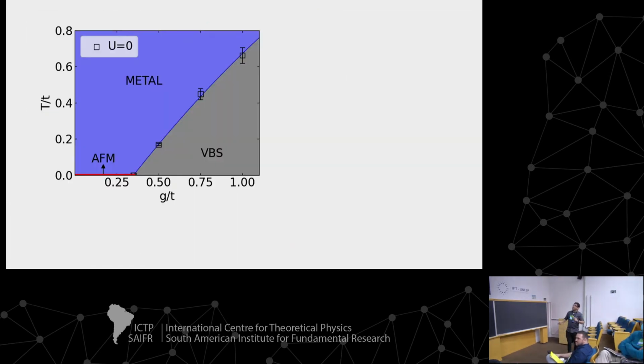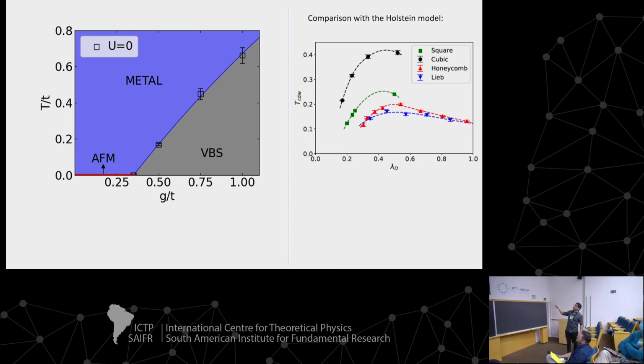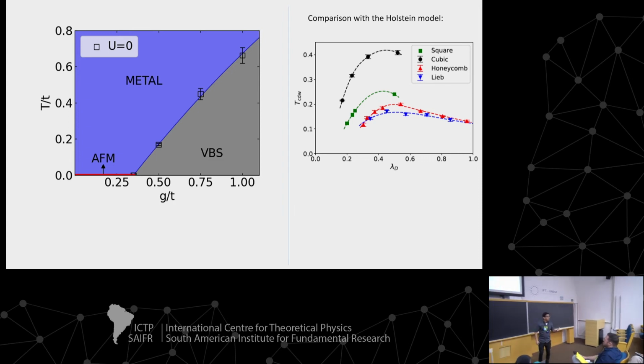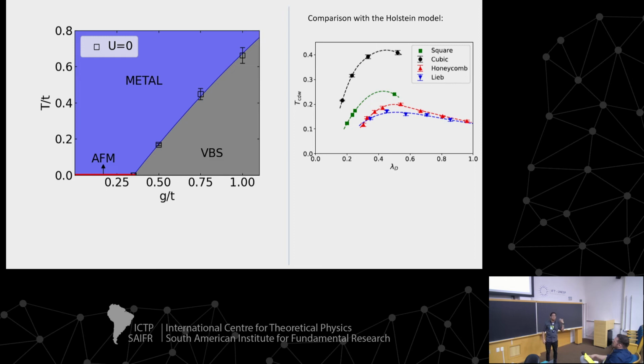And the main result that Sebastião has shown is basically we have this phase diagram, finite temperature phase diagram, in which the temperature increases a lot. And this is a lot indeed. I will show you one result so you can compare. For instance, here is the phase diagram for many different kinds of lattices for the Holstein model. And in the Holstein model, we cannot reach such high temperature. And more, we have a maximum. And the maximum is because of the creation of this heavy polaron. And here, we don't have this maximum, although we have much larger values of interactions. So these two axes can be compared directly. So this is a very clear indication, at least for us, that we can have high temperature collective modes in this kind of problem because the mass of the polarons is light. So this is the main idea.